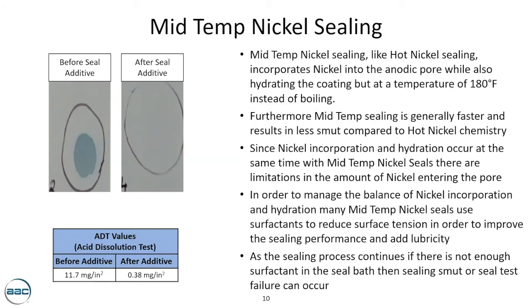Just because you had a failure by a blue dye stain test or even an ADT doesn't necessarily mean you need to dump the whole bath. There are ways to salvage that bath without dumping it and saving yourself the pain of dealing with the nickel discharge. So what you'll see here again is when we did our ADT values, you'll see the 11.7 milligrams per square inch is an improvement compared to the hot nickel of 13.